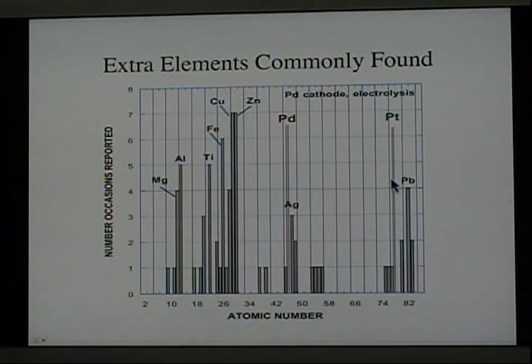Well, in an electrolytic cell, when the anode is platinum, platinum is transferred to and deposited on the palladium cathode surface. So platinum would be available to suffer the same kind of reaction that the palladium suffered. In other words, deuterons or protons would go into the platinum nucleus in sufficient number to build up to form these elements. This is an example of what is called transmutation, and it's an aspect of the process that is being seen more and more often as people look with more detail at the production of unlikely elements.